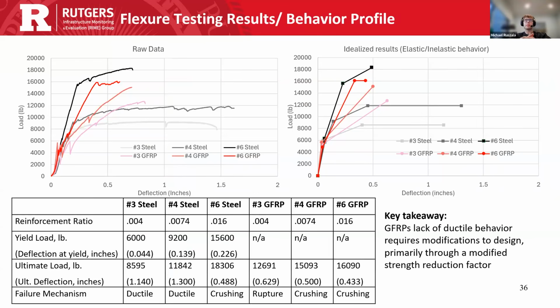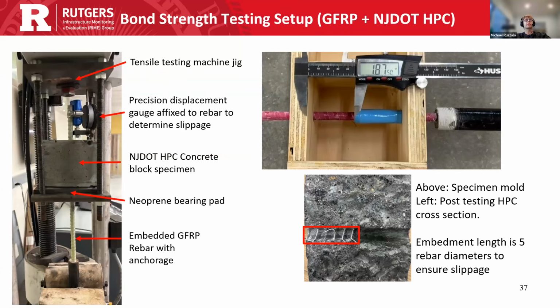So going into the data from this test series, we can see the raw data and the idealized results that are just the cleaned results based on the slopes. So we can see the more drawn out behavior of the steel rebar as expected. We can see a more brittle failure for the over-reinforced steel section and a characteristic brittle failure, or concrete crushing, of all of the GFRP members. But we do see that for the rebar size, it does reach a higher capacity. So it is an excellent material in that regard, and that's why design compensates for these differences.